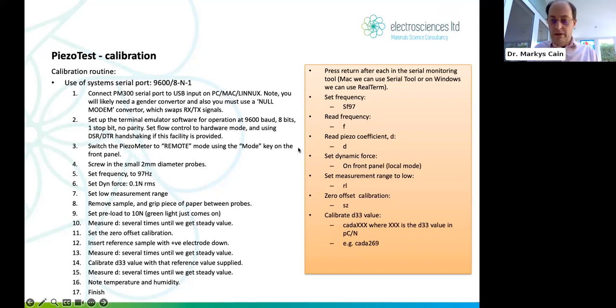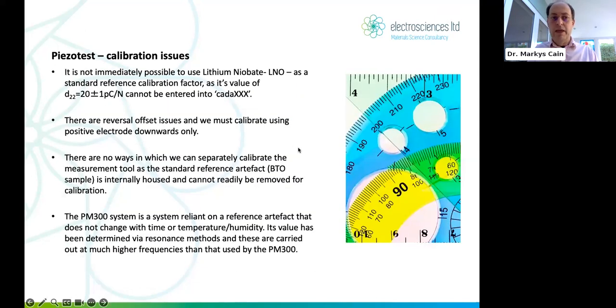Okay, so calibration issues. Now, calibration. What do we do? How do we calibrate the machine? What's the best way of calibrating the machine? Lithium niobate and quartz are two materials which have a very well-defined piezoelectric coefficient. They're very well, theoretically defined, actually, these two material systems.